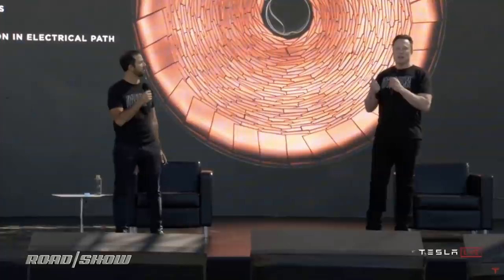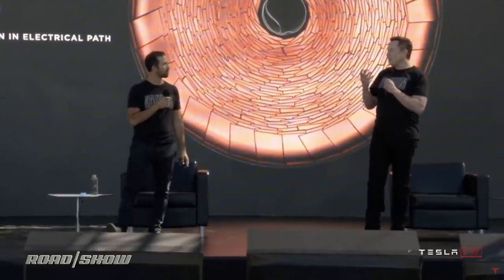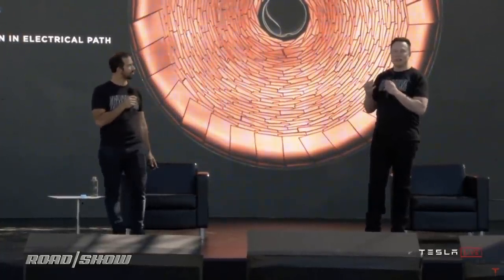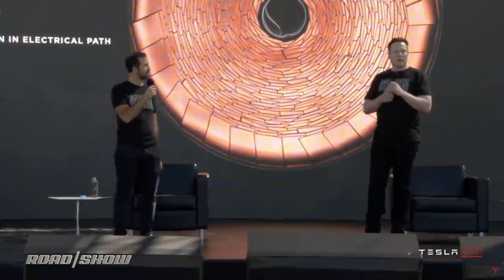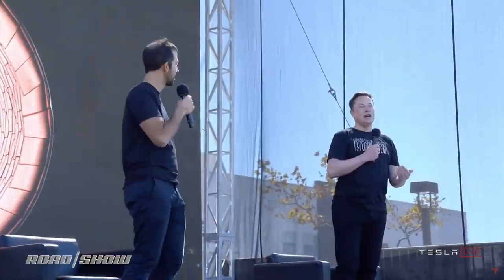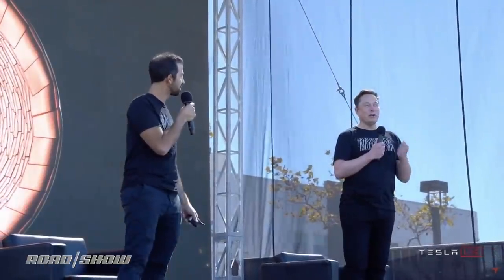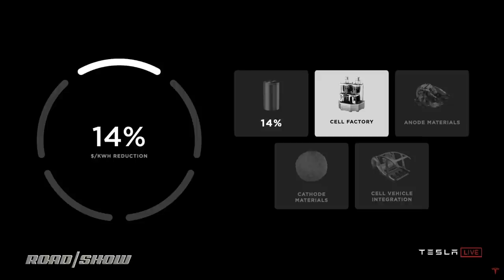Basically the distance that the electron has to travel is just much less. So you actually have a shorter path length in a large tabless cell than you have in the smaller cell with tabs. This is a big deal. So even though the cell is bigger, it actually has more power. So just the cell form factor change enables a 14% dollar per kilowatt hour reduction, just that cell form factor change.